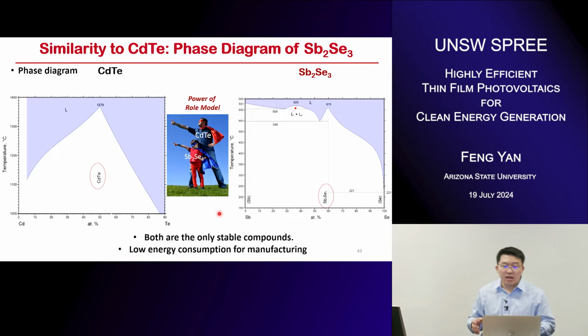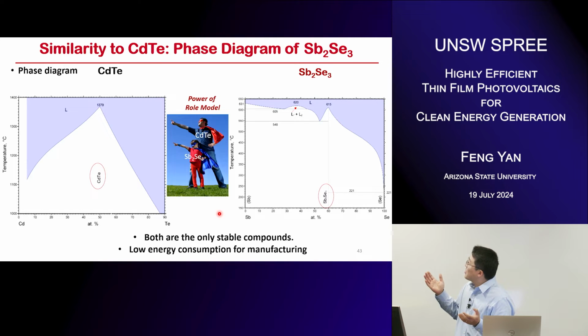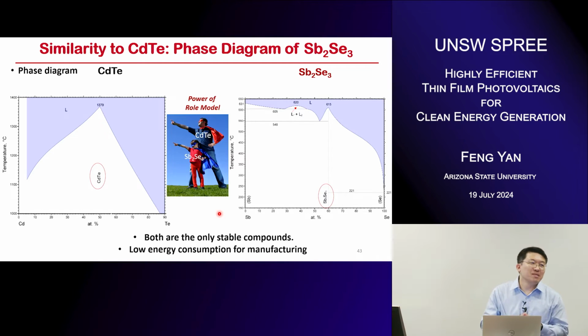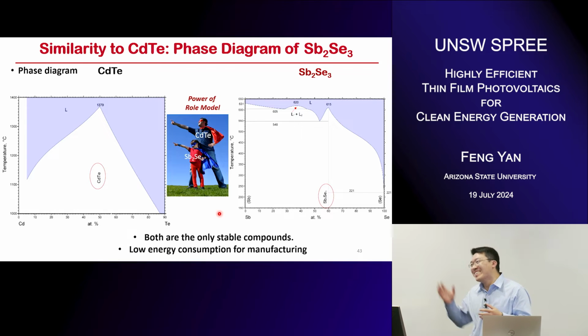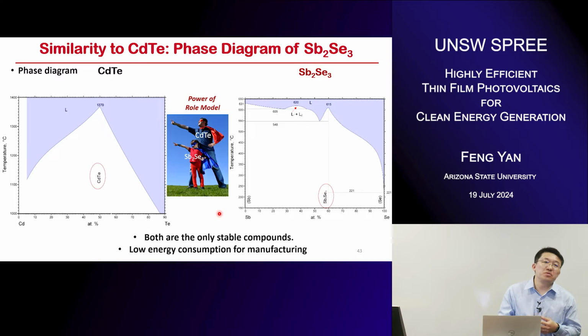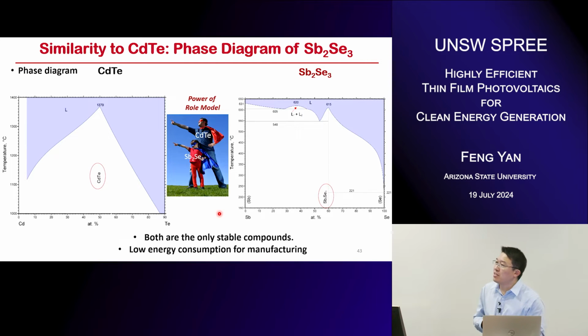Another thing, if we want to grow it, from the materials view, the good thing is the phase diagram, because I'm from a materials science background, and the phase diagram is another guideline to help us evaluate the material's thermal behavior. Cadmium telluride is the only compound between the cadmium and the tellurium, and it has a pretty high melting point, you can see close to more than 1000 degrees.